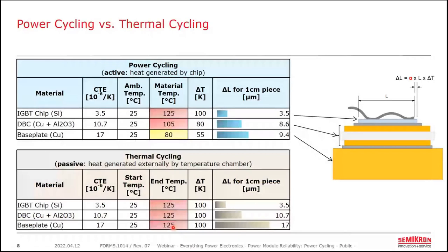In terms of modeling the life, it's really more accurate to stick with power cycling, where you're actively heating the chip. And if you want to stress, for example, the base plate solder more, that's usually done with longer temperature cycles. So I mentioned our model's good up to 60 seconds. In your power cycling test, you can certainly heat up to longer times on the order of minutes. And that allows the heat, of course, to get down in the base plate and things to warm up a bit more. And you'll have much more base plate solder induced failures and things like that.